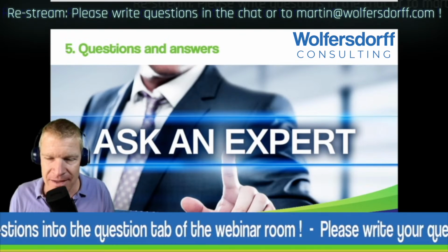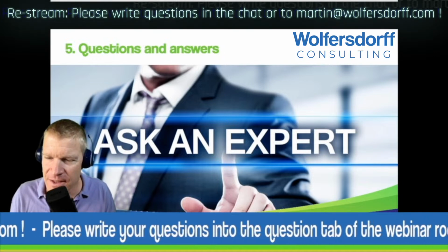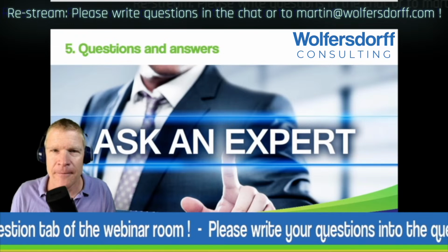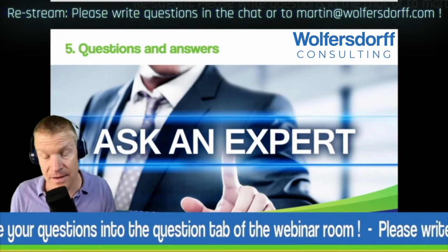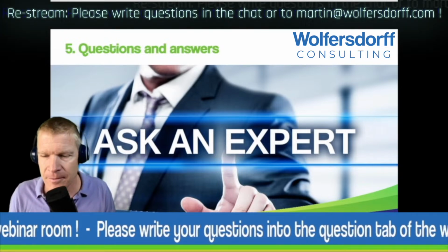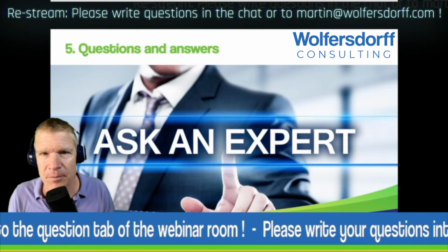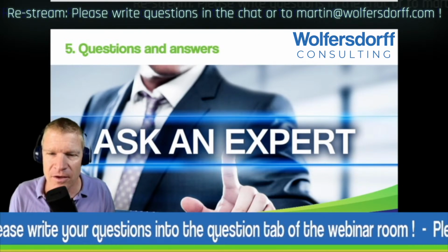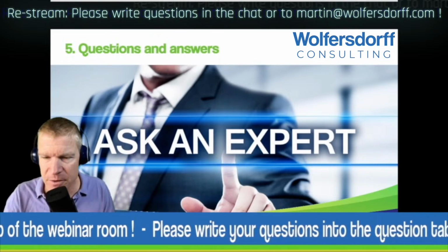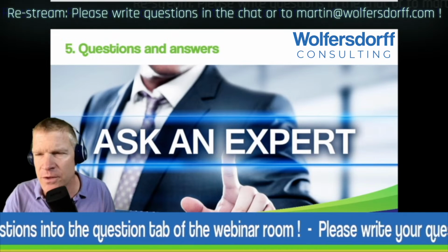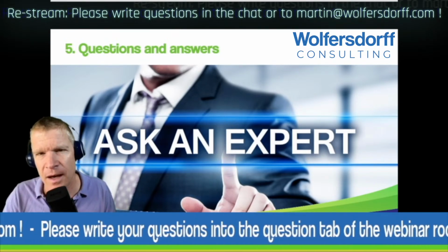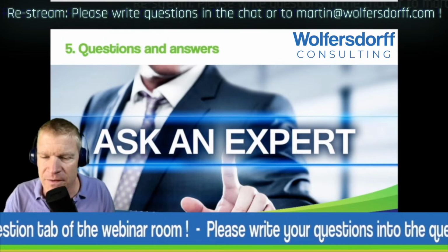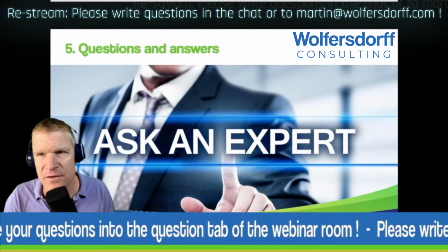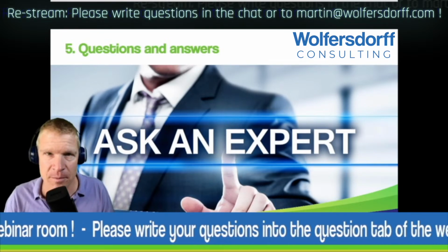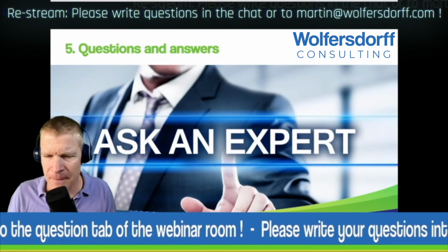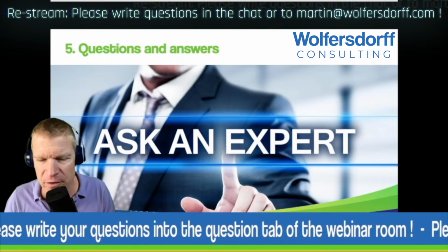Derek from Colloids asks: do you have any data on functional groups on the carbon black surface and how this compares with standard furnace carbon black? I personally don't, but my information is that many of the surface groups are actually being burnt off under the pyrolysis conditions. However, I would recommend reading an academic article by Christian Roy, which is something like energy science of carbon blacks and recovered carbon blacks, measuring the specific surface energy, not the surface groups, but the surface energy of the different types of carbon, both the recovered carbon black and the normal carbon black. And he might have something on the functional groups as well.